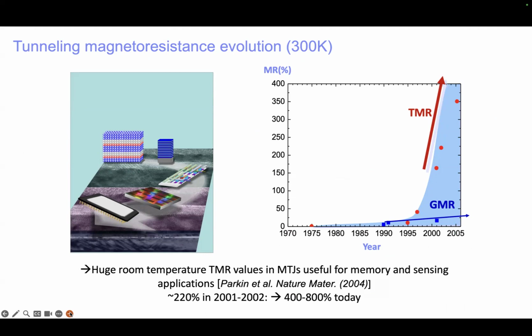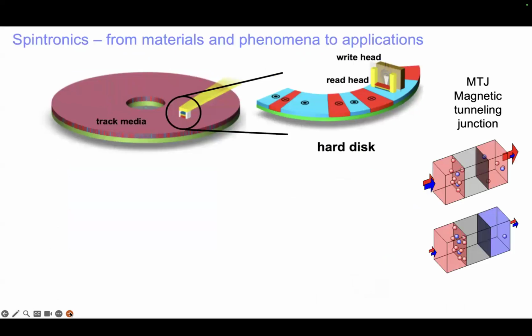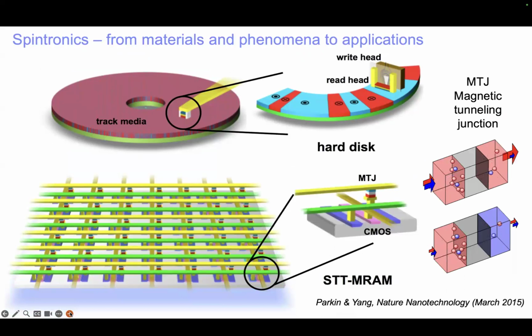So this makes them extremely interesting, not only for sensing, magnetoresistive sensors, but also as a memory device. And this is something that we proposed first in 1995, so it's a long time ago. And this is the concept. On the bottom, you can see a so-called cross-point array. You have arrays of wires in opposite directions, and at each intersection, you place a tunnel junction where the current flows perpendicularly through the device from the lower to the upper electrode. And then we could store information, no longer as a sensing device, but as a memory device. We store information as the direction of the magnetization of the moment of one of these layers in the tunnel junction shown on the right-hand side.